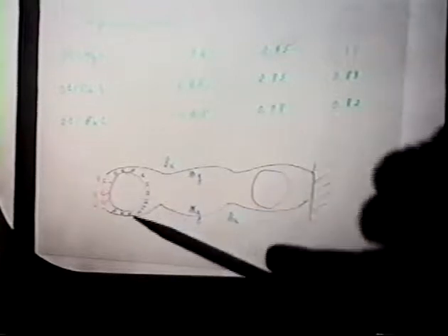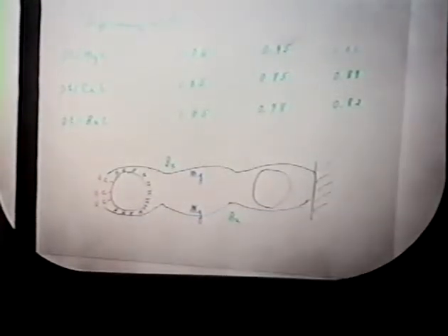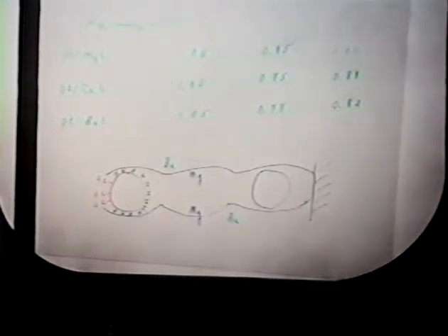But what I think is happening here is these are catalysts that are made such that you're sort of blocking the ends of the pores, and the hydrogen can chemisorb and move around the whole particle, but the CO can only decorate that portion of the particle which hangs out of the pore. We wanted to look at how the dispersion and the hydrogen to CO ratio were affected by calcination. We've been doing all of these at rather low calcination temperatures, 350 Celsius, and then reducing at the same temperature, primarily because we wanted to keep as much of the platinum inside as we could.